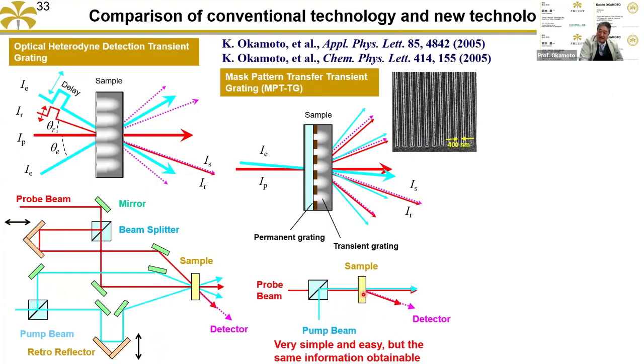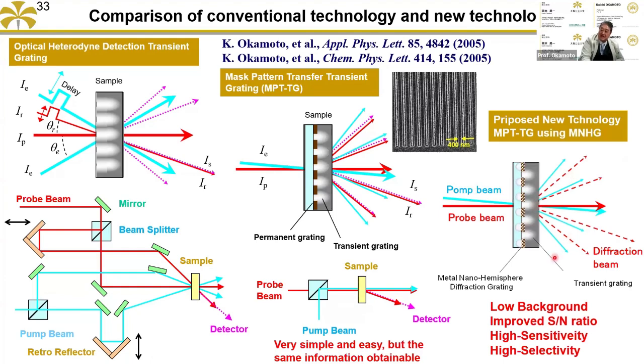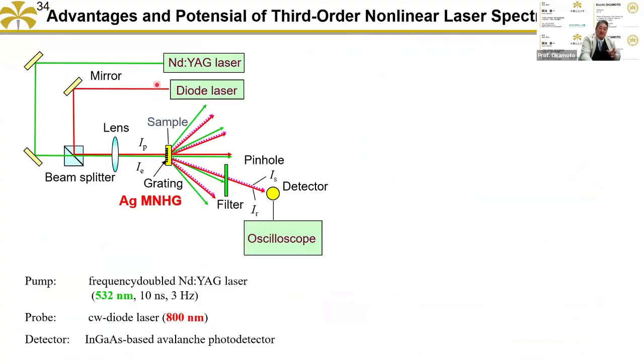But the problem is that the signal beam and the diffraction beam from this structure are in the same direction and the same color. That's why it has a large background, and the SN ratio is very low. But if we can fabricate a wavelength dependent grating, the pump beam is deflected but the probe beam is not. In that configuration, we can obtain a low background, improve the SN ratio, and get high sensitivity and high selectivity.